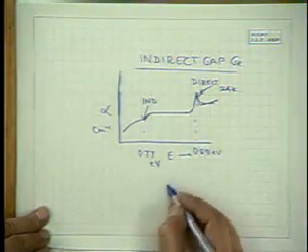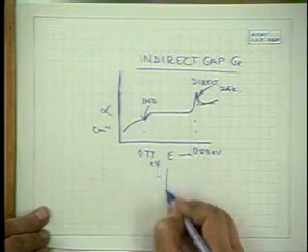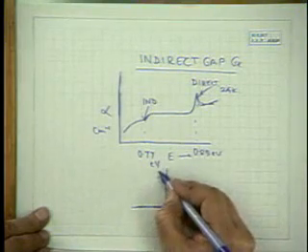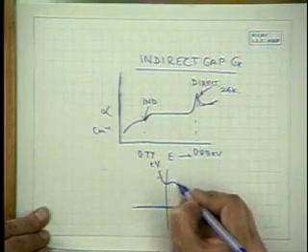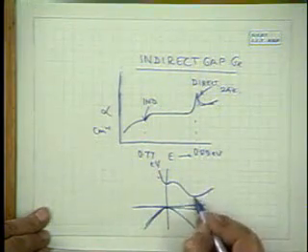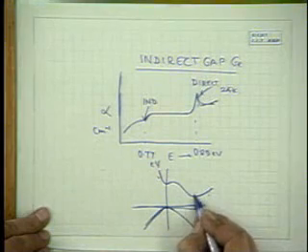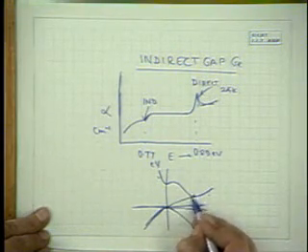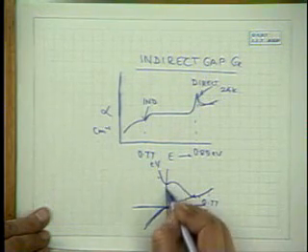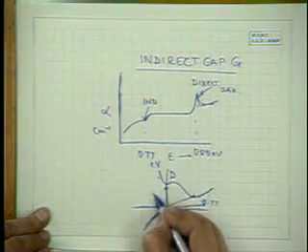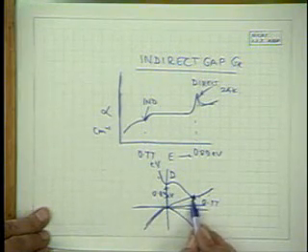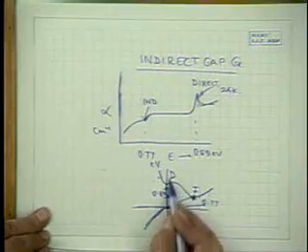Remember, the band structure of germanium can be shown as follows. To explain this result, the indirect gap is about 0.77 eV, and there is a direct gap here at about 0.89 eV. So there are excitonic absorptions associated with both the indirect and direct gaps.